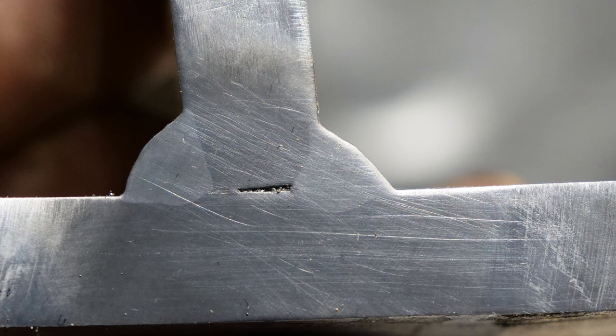But both of these actually penetrated past the root. Especially that right one, I really like the way that right one looks. Keep in mind this is what you would expect on 3/8 plate with 160 to 180 amp MIG welder. If you have more power than that you could probably see a little bit better penetration with flux core. If you have less power than that, like 140 amp, good luck. It's just not gonna get to this point with 140 amps on 3/8.